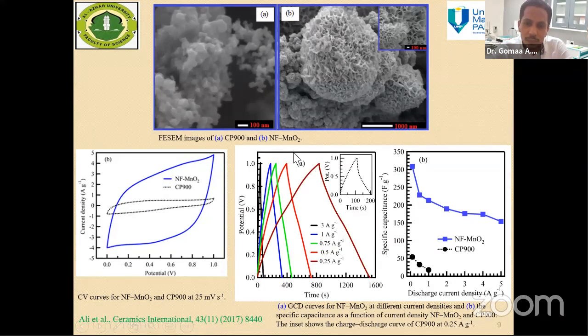The same for charge-discharge. It was tested at different current densities, showing linear charging and discharging curves. For specific capacitance calculations, it shows a high specific capacitance of around 300 farad per gram at a current density of around 0.1 ampere per gram, which is around 6 times higher than the dry cathode powder. So by converting the cathode powder of the spent carbon battery into nanoflower morphology, we can apply this product in supercapacitor applications and get more than 6 times higher specific capacitance. This work was also published in Ceramics International 2017.